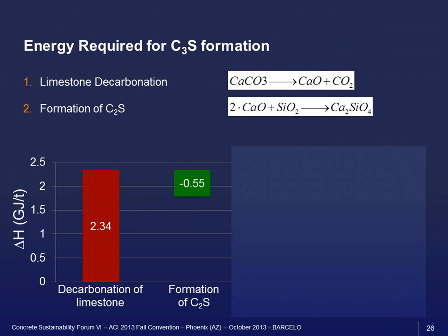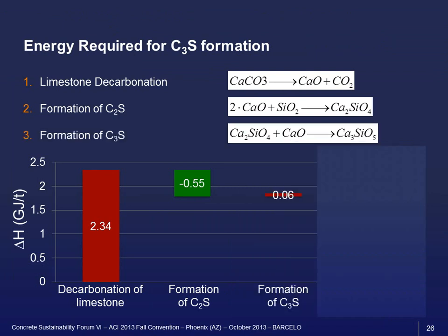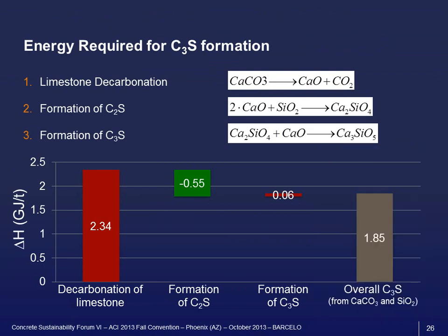After that, we have the formation of C2S from the lime that is being produced here and the silica that we put in the raw mix to form C2S. And this reaction indeed releases a little bit of heat. And finally, C2S combines with additional CaO to form C3S. And we have the overall C3S balance here with 1.85 gigajoules per ton of C3S.